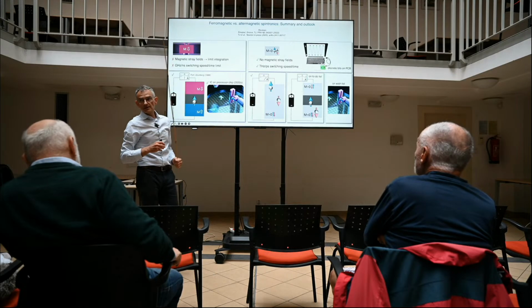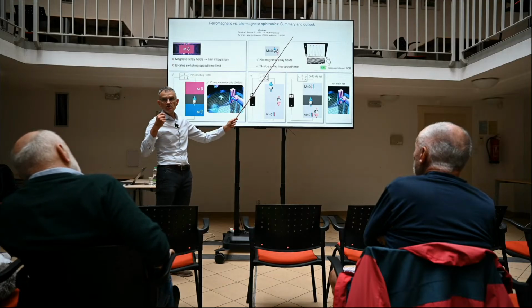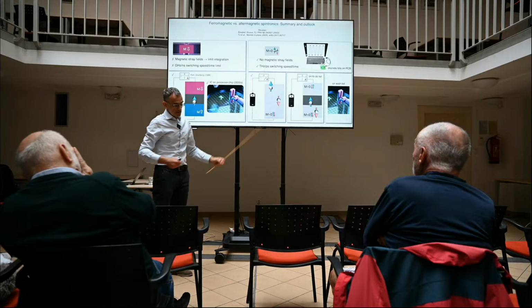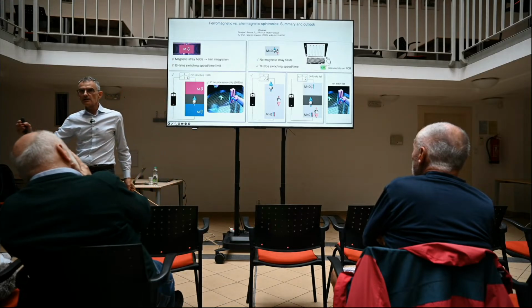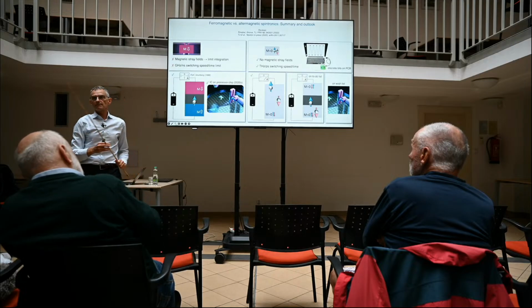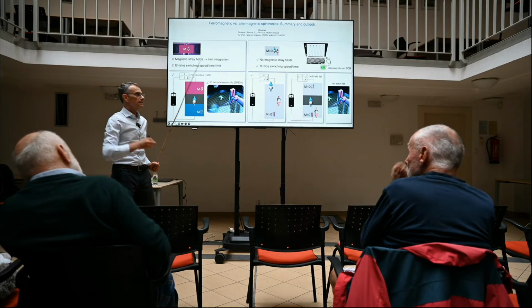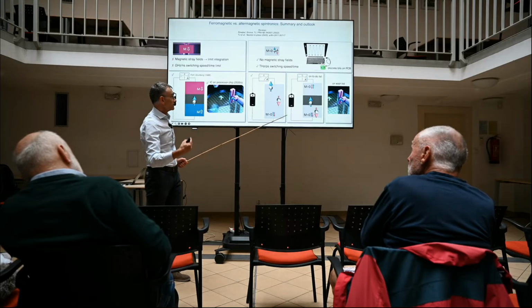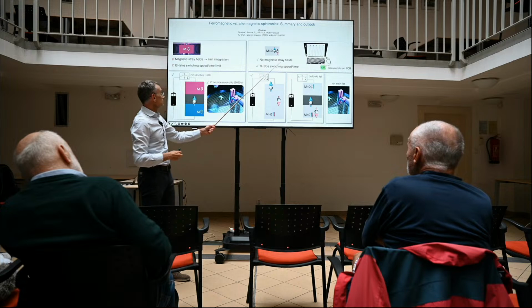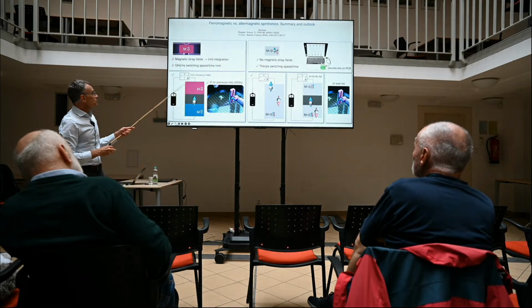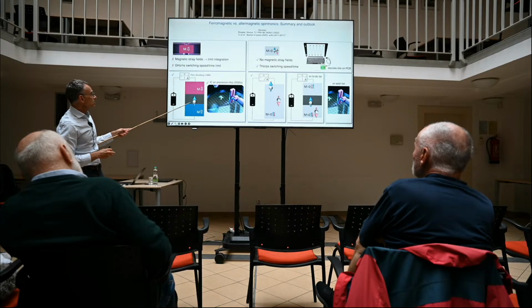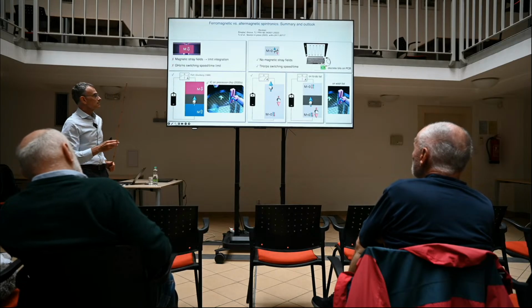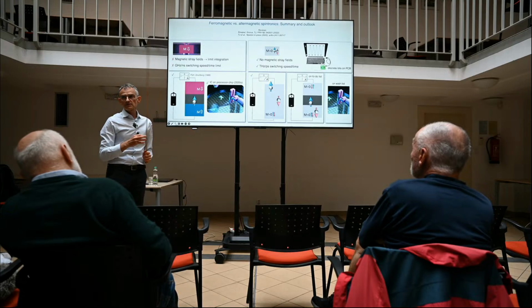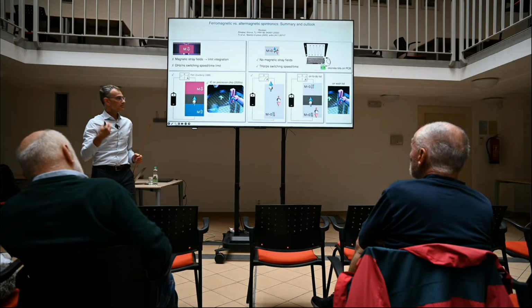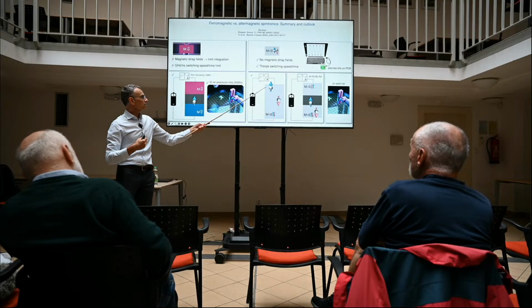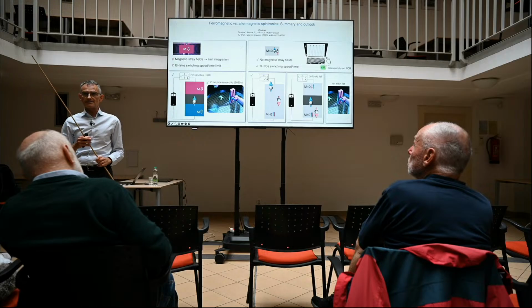that we can operate them electrically, both reading and writing. They generate zero stray fields, and we can switch them by pulses, electrical, optical, scaled down all the way to picoseconds or even sub-picoseconds without any excessive increase in switching energy. So that has been demonstrated already. But we also know that for the successful operation of these devices, we need to have spin polarized currents. This is something that we already also demonstrated in altermagnets. We already know and experimentally demonstrated that if we run electrical currents, they will be spin polarized in altermagnets.